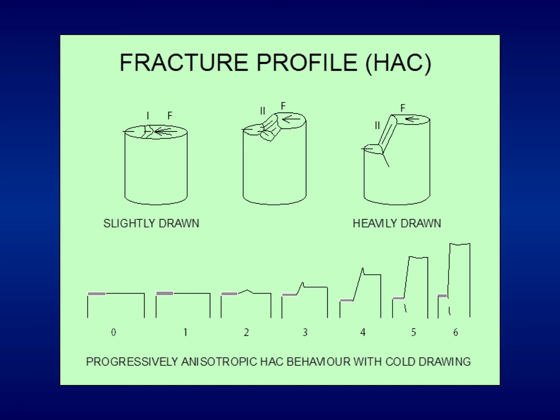With regard to crack paths, micro crack paths, or hydrogen-assisted cracking paths in the form of fracture profile, here we can see 3D views and profiles for different degrees of drawing. Slightly drawn steels fail in mode 1. After the fatigue pre-crack, there is a mode 1 propagation, subcritical cracking, and final fracture by cleavage.